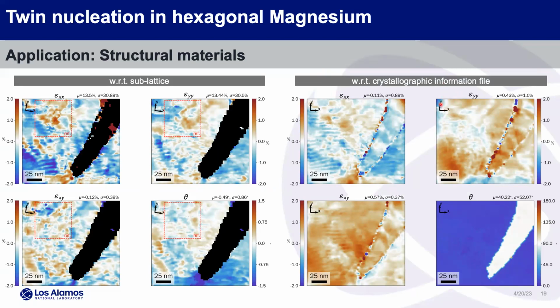So like Y is top and X is right. And then the crystal was oriented along 001 here. What we saw is a strain state that changed in the X direction from compressive to tensile at the tip and then back to compressive. And then we're able to get the strain inside of the twin.